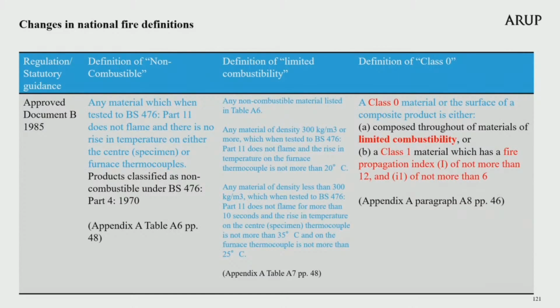However, in 1985, the definition of Class 0 was significantly changed. First, the definition stopped relying on non-combustible materials, and instead a Class 0 material or surface of a composite product could be composed throughout of materials of limited combustibility, a lower standard. Secondly, the requirement to consider the substrate with the surface was removed from the text in the statutory guidance document. This remained the definition to the time of the Grenfell fire.